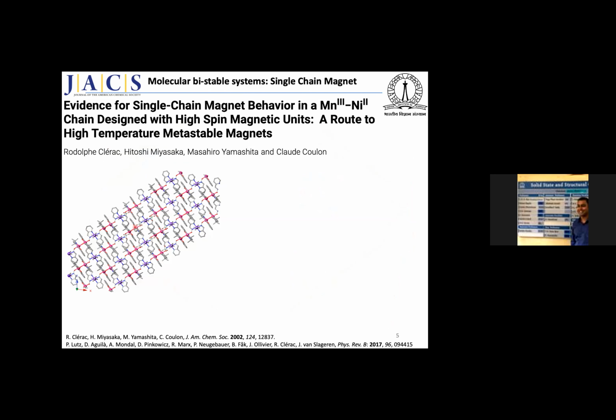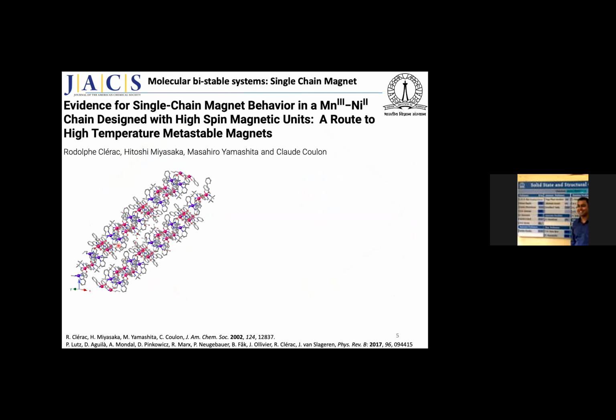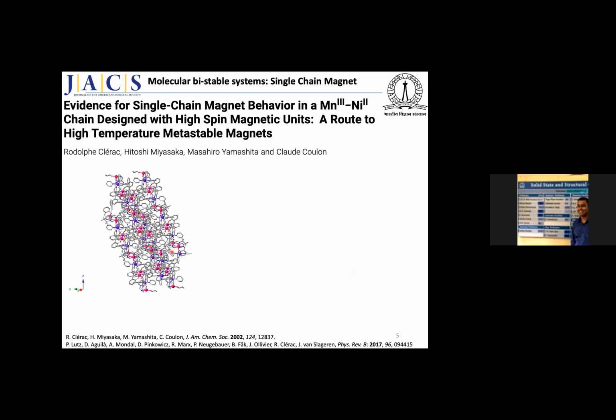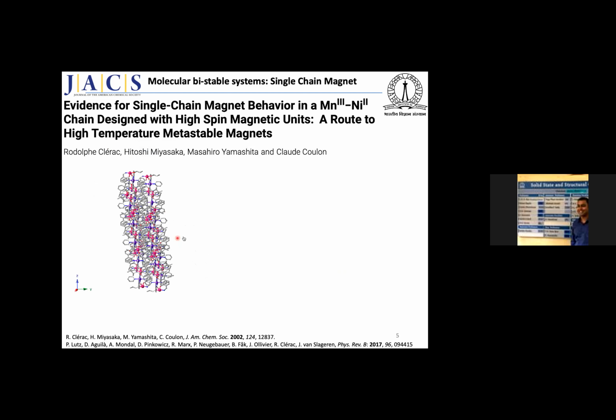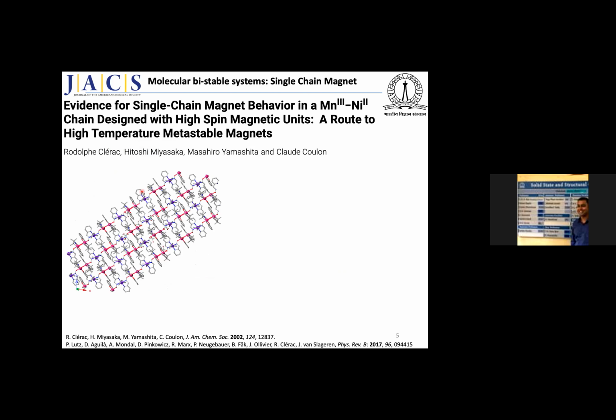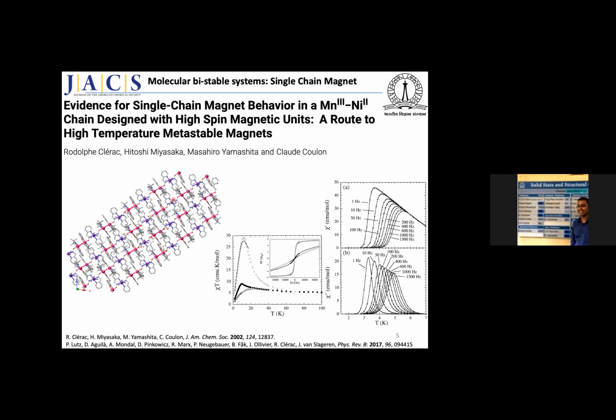So here you can see this is a manganese 2 unit. Manganese 3 is connected by this oxygen bridge with these ligands, and they are linked with the nickel pyridine aldoxime ligands, and they are having a 1D Ising type of chains, and these molecules or these systems exhibit the first single chain magnet behavior.